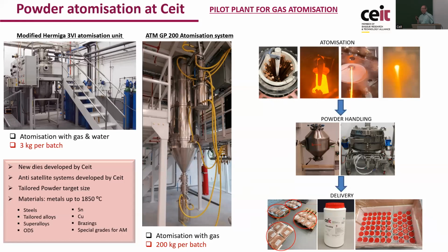At Ceit, we have two facilities to produce gas atomized powder. The first one is a small atomizer, of laboratory scale, where we are able to produce 3 kilograms of powder per experiment. And we have as well a big atomizer where we can produce 200 kilograms of powder per experiment. In the process, basically, what we do is to charge the raw materials in an induction melting furnace. Here we melt the materials and they get alloyed, the different alloying elements. When the melt is homogeneous, we lift up this rod, which is called the stopper rod, and the metal is driven into the atomization chamber.